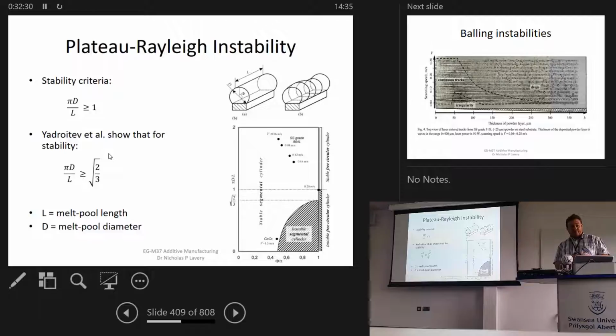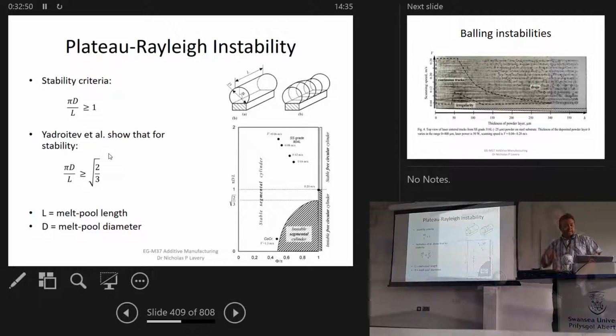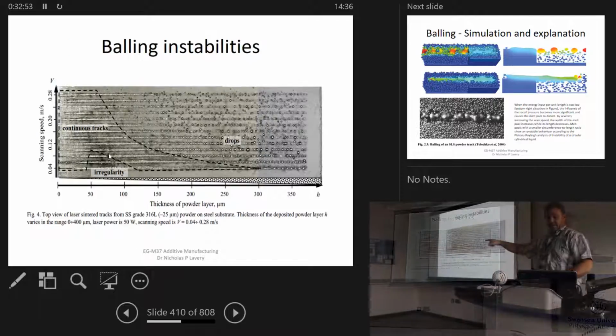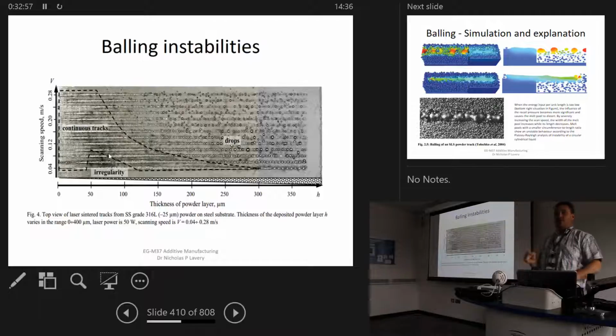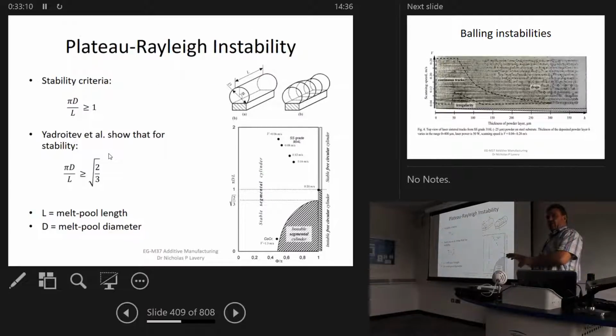So you have these long tubes of liquid which are solidifying, and potentially your wetting angle, your surface tension, is changing as a function of temperature. You're getting a longer melt pool that eventually starts to solidify. It gets a bit too long and becomes unstable, and then it starts to solidify and goes back. So I'm just going to show you quickly here some melt tracks. If you take a quick snapshot of that, you could be thinking you're looking at a series of water columns dropping and breaking up into droplets on the way down. But these are actually melt tracks that have been laid down. So that instability into droplets is thought to be very much a consequence of a Plateau-Rayleigh instability at the fluid level.